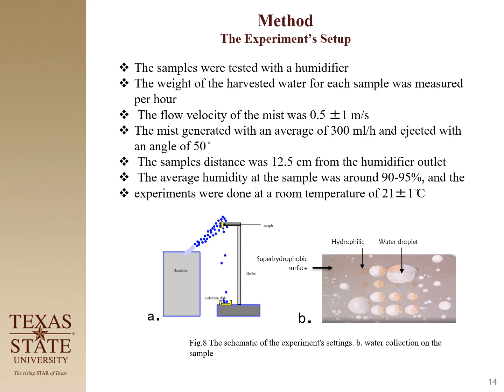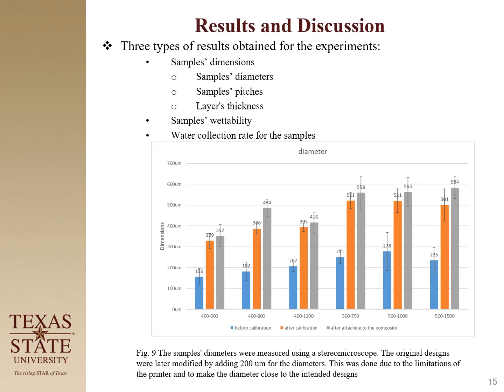I put a Petri dish to collect the water. Each run was 1 hour, and I weighed the water after that. Of course, I also measured the flow rate of the mist coming from the humidifier. And you can see in the picture how the growth can be controlled on the hydrophilic parts of the sample.